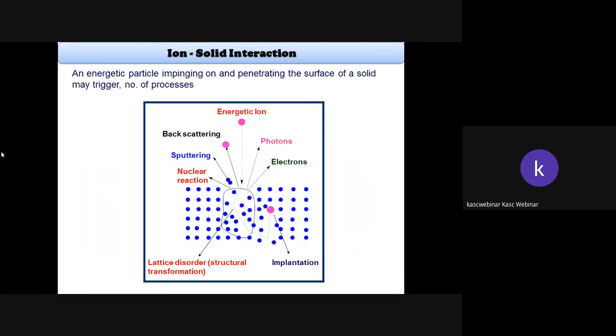So if an energetic particle impinges on a material and penetrates the surface of a solid, it may trigger a number of processes. For example, the incident energetic ion may rest inside a material, which is called implantation. It may eject the atomic materials present on the surface of a sample, that's called sputtering, and certain nuclear reactions are also possible. In some cases, phonons may be excited due to the impartment of kinetic energy to the lattice material, and ultimately we can expect lattice disorder inside a material, that's called structural transformation. There may be a recrystallization or an amorphization of the material.